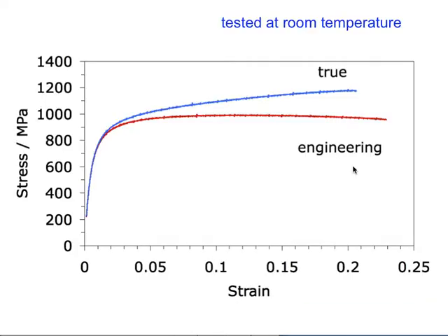And it's quite remarkable, this was designed purely by calculation, all right? We did not expect this bizarre looking microstructure, but it happened. And look at the stress strain curve, huge amount of elongation, all right? And if I look at the retained austenite content at the beginning, it's about that much, 15%.